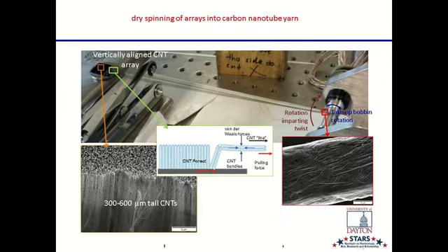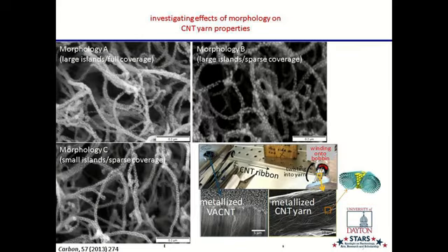So we thought about how this works, and we realized that there's a trend. It's really a simple trend. There's a binding energy of each element, how much energy it takes for the atoms to be combined or separated. That energy dictates how big those islands are, how many of those islands there are. So we thought about the parameters that drive that and came up with some ways to make gold particles look just like titanium particles and vice versa. So we overcame that barrier. And that's great because now this is how we do it.